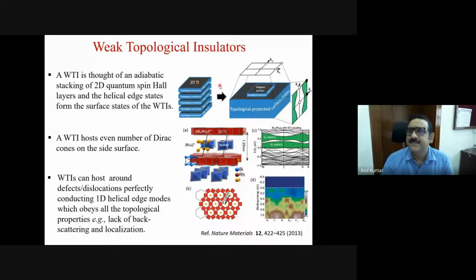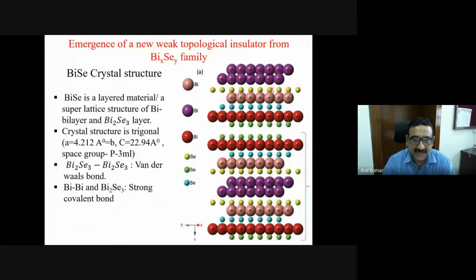But what can happen if you have a small structure on top of it? Because when you do exfoliation, there will be half-covered surfaces. And it was shown theoretically now that these surfaces also exhibit topologically protected surface state, which I will prove now it is indeed the case. And then we have discovered a new material in our lab, which is a new topological insulator. This is from this BiSe family, and the crystal is just BiSe.